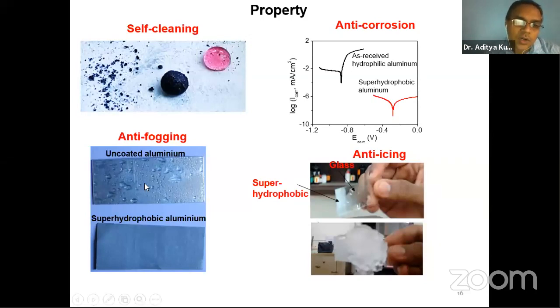And this uncoated, what we have done, we have put both samples into the freezer for a longer time, like overnight. And after that, we put them into the humid atmosphere. So immediately on the uncoated metallic surface or aluminum, you see lots of water droplets, meaning the fog onto the surface, right? But on super-hydrophobic coatings or super-hydrophobic aluminum surface, we can't see any fog. So super-hydrophobicity also shows anti-fogging nature.